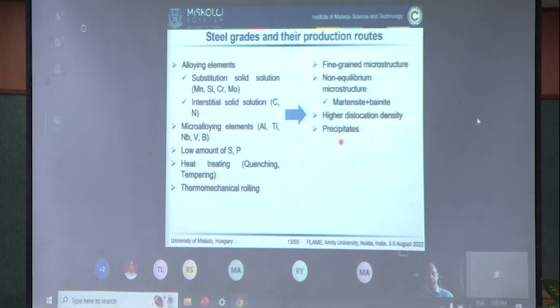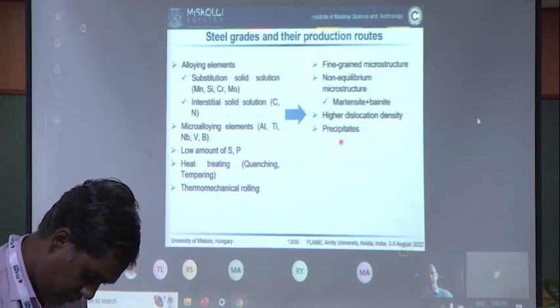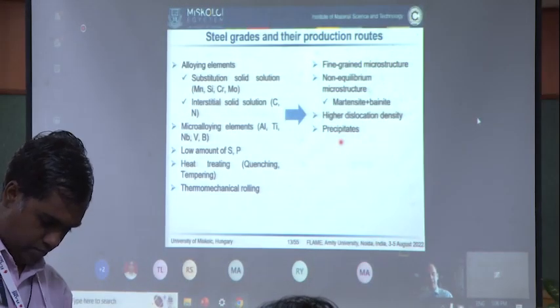How can they achieve these high strengths? Besides the processing routes, of course, different kinds of alloying elements are needed. Firstly, I should highlight the substitutional solid solution elements, such as manganese, silicon, chromium, or molybdenum. And besides them, there are also some interstitial solid solution elements, of course carbon, and in some cases nitrogen. Microalloying elements generally have a very important role in high-strength steels, especially in high-strength low-alloy steels. We can find aluminium, titanium, niobium, vanadium, and boron in this kind of high-strength steels.